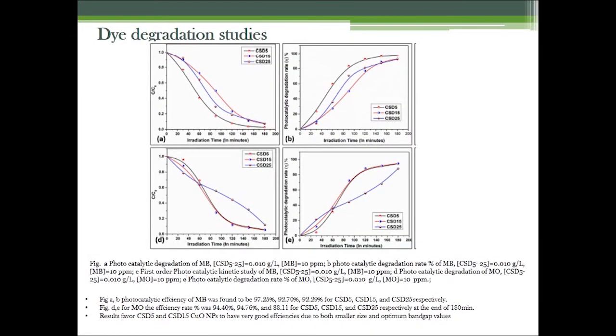Coming to the dye degradation studies, upon the confirmation of the nanoregime of the synthesized particles, we were curious to know about the efficiency of the synthesized nanoparticles for the degradation of the dye. So we have selected two different dyes: one is methylene blue and the other one is methyl orange. In the first figure A, you will be able to notice the photocatalytic efficiency was found to be around 97, 92 and 92% for 5, 15 and 25 ml of extract.